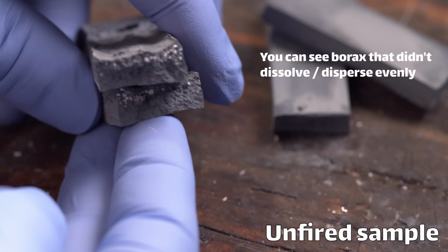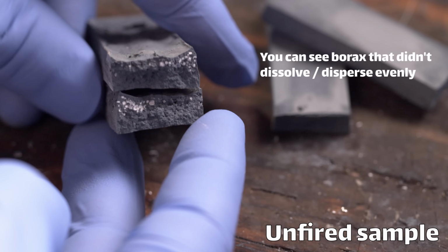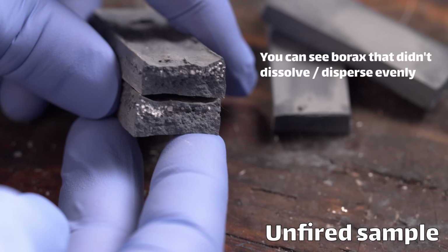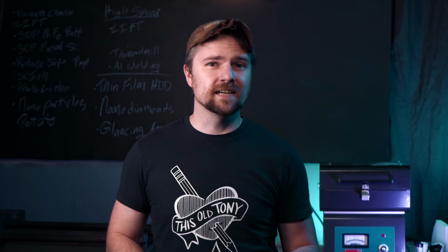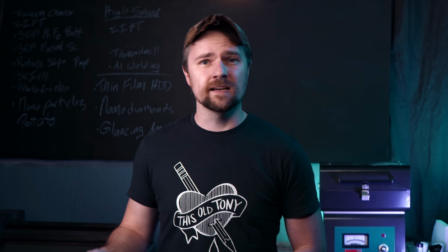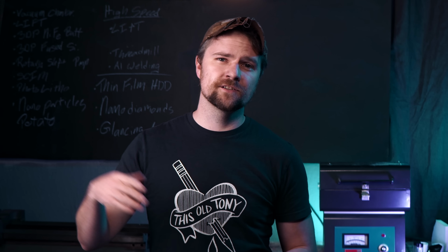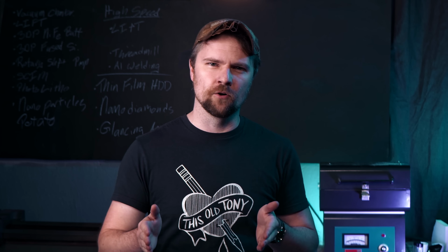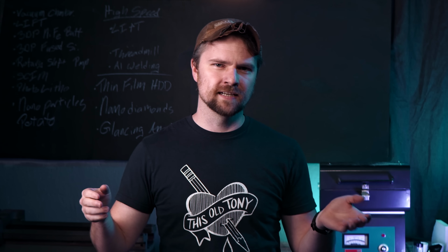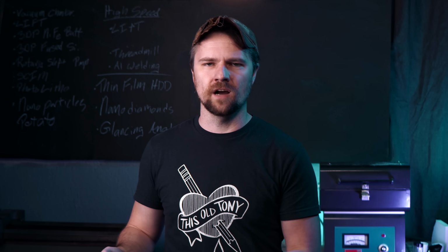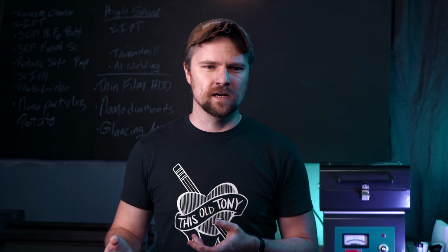Whether I did something wrong mixing the ingredients incorrectly, not homogeneous enough, impurities in the base materials. The furnace I'm using doesn't have particularly good temperature control, so maybe it was fluctuating too much. Maybe this effect only works at 600 degrees in a very narrow band, but no more or no less. There's a lot of different ways this could have gone wrong that was essentially something about my setup here.